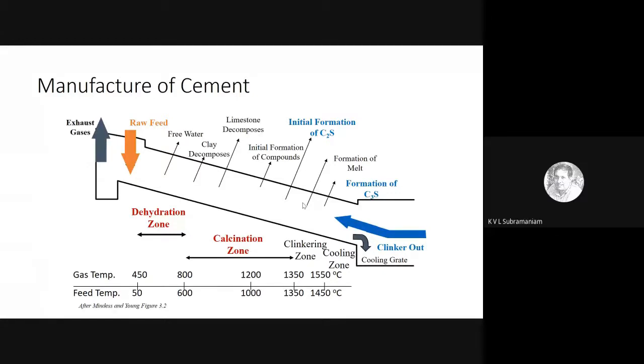Then I have the clay decomposition. The clay decomposes into its constituent ingredients. So it basically decomposes, and I get my silica from the clay, I get the alumina from the clay, I get the iron oxide from the clay. So these start decomposing. So it decomposes it into its component oxides or constituent oxides.